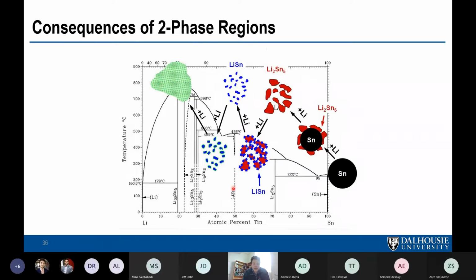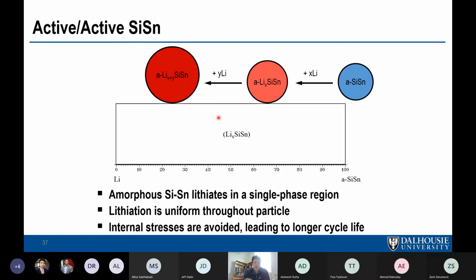This expansion, or the volume of this phase, is about 100% more than this phase per host, and so you get large strain again and cracking, and the particles fracture more. And then you enter another 2-phase region, another 100% volume expansion between the phases, till the whole thing's about 300% volume expansion when you get to the end of it. And by the time you get to the end of it, you're left with something that's highly fractured. And if you try to delithiate and these particles start to shrink and pull away from each other, you don't get much capacity at all. So that situation is not ideal.